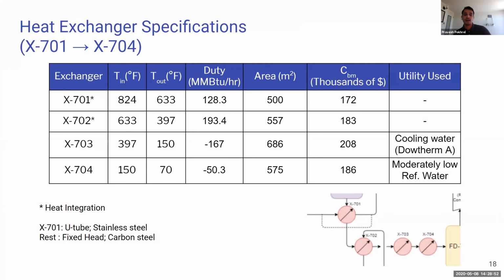So we had a total of 10 heat exchangers in our system, with heat exchangers 701 and 702 participating in heat integration, as Chance mentioned earlier. We cool down the reactor effluent stream by using the inlet VGO flow, which was further cooled down by the stream coming out of the first flash drum to around 397 degrees Fahrenheit, which was further cooled down by using cooling water in heat exchanger 703 to 150 degrees Fahrenheit. And then we use heat exchanger 704 to cool it down to 70 degrees Fahrenheit by using moderately low refrigerated water.